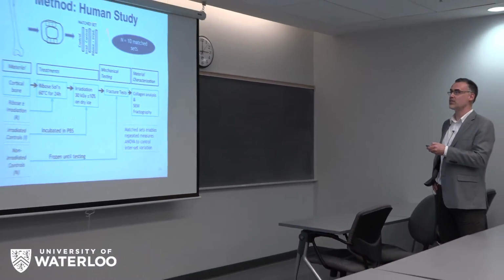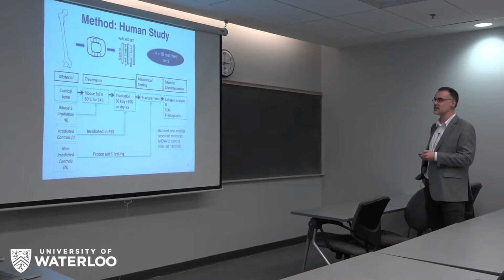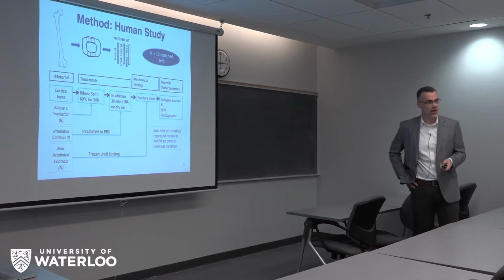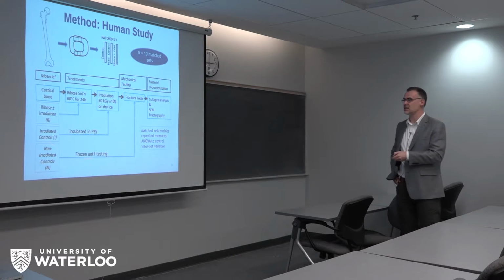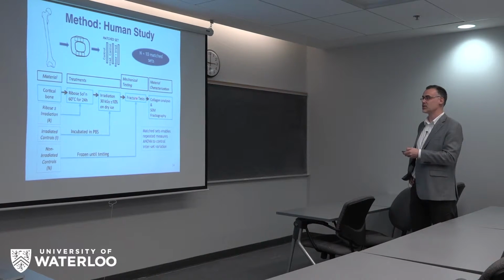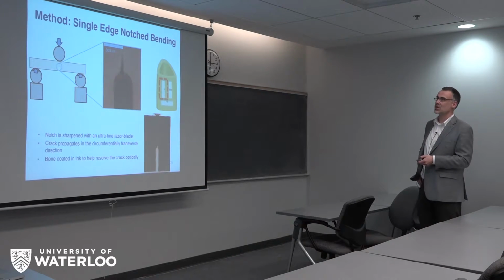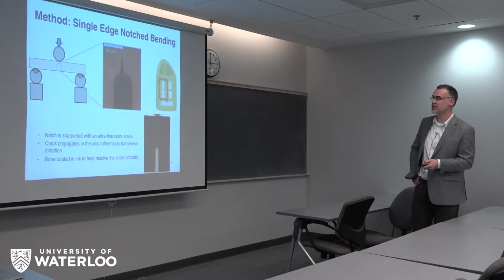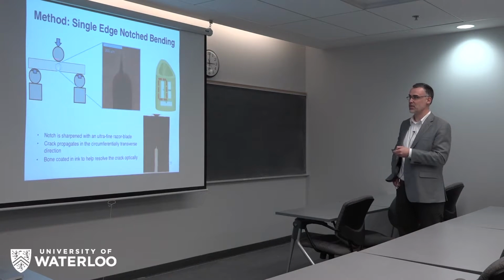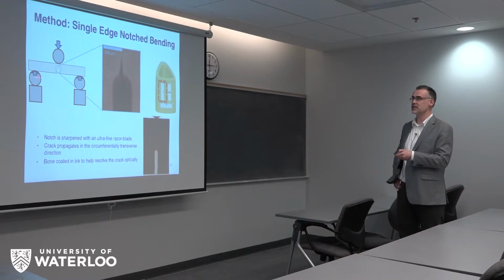And so, similar to the last study, but with far less groups because of the dimensions of our specimens, we took the diaphyseal cortical bone, machined out sets, in this case 10 sets, from, again, male human donors, and the same type of design, but doing fracture testing instead. And so we use the single edge notch bending configuration. So it's basically 3-point bending again, but with a notch machined into these specimens.